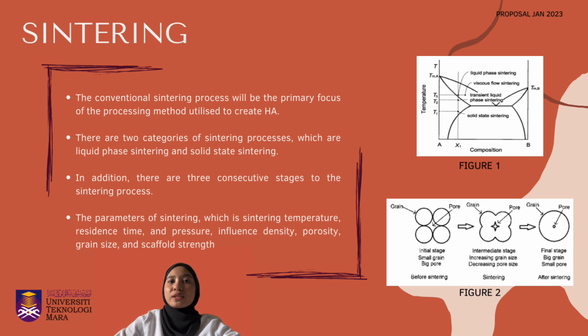Different sintering processes at different temperatures are shown in Figure 1. In addition, there are three consecutive stages to the sintering process, namely contact formation, shrinkage, and coarsening. Figure 2 depicts a straightforward model that uses spherical particles to schematize every stage. In the first stage, necks form and expand between particles. Meanwhile, the pores are still open during the intermediate stage.